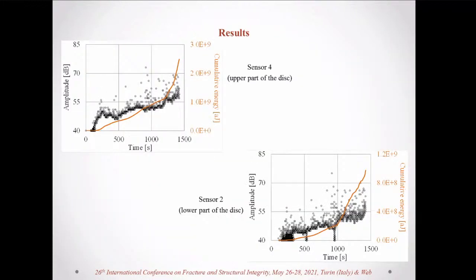Indeed, this seems to be right based on the slope change observed on the cumulative energy recorded from the acoustic sensors at the lower part of the disc. We see that the rate of increase is detected at the same time instant, and it is about 200 seconds earlier than the respective slope change at the upper part of the disc.